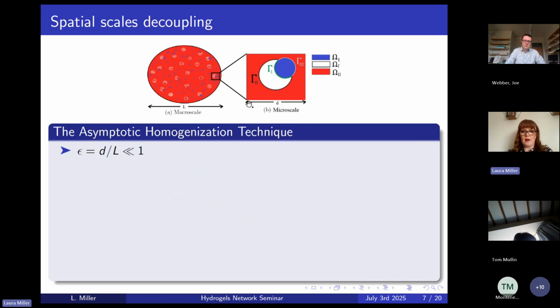So what I have done here is just resketch what I had in the previous slide. And you'll notice again, I have got these length scales D and L. The first thing I have to do if I'm going to apply the asymptotic homogenization technique is ensure that my scale separation parameter epsilon, which is a ratio of this length D to this length L, is much less than 1. This has to be the case to ensure that there's a sharp enough separation between my two scales to allow the upscaling to work correctly.